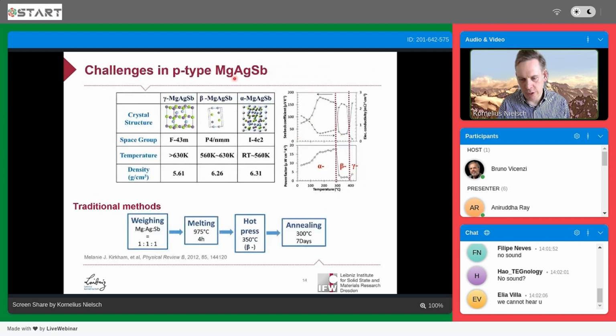Talking about magnesium silver antimonide, which is a very promising P-type material, this material unfortunately also has a phase transition. This phase transition occurs at roughly 300 degrees, from an alpha phase to a beta phase. And you always try to operate a device below this phase transition of about 300 centigrade.